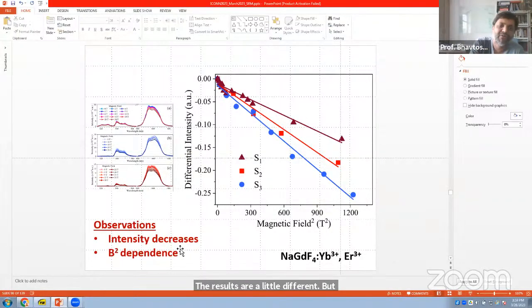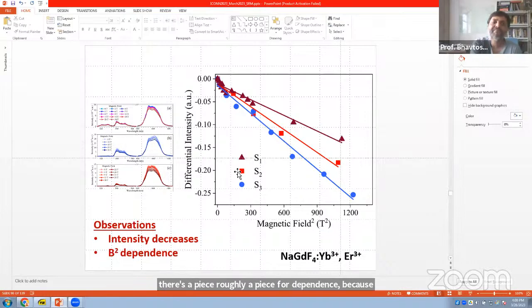Basically it is very sensitive to the local environment, because the kind of electric field perturbations you generate will affect the response very strongly, I would imagine. But nevertheless, you see a decrease in the intensity, and there's roughly a B² dependence, because I've plotted this as B² versus the change in the intensity.